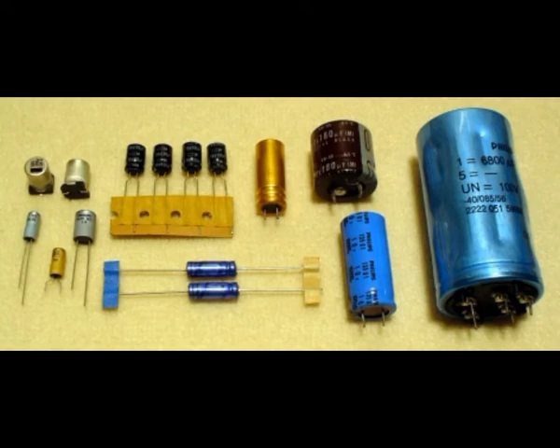The situation improved over the next 20 years and the capacitors became good enough for longer life applications. This led in turn to a previously unnoticed water-driven corrosion, which weakens the stable dielectric oxide layer during storage or disuse. This leads to high leakage currents after storage. Most of the electrolytes in that time contain water, and many of the capacitors reach their end of life by drying out. Water-driven corrosion was the reason for recommended precondition instructions.